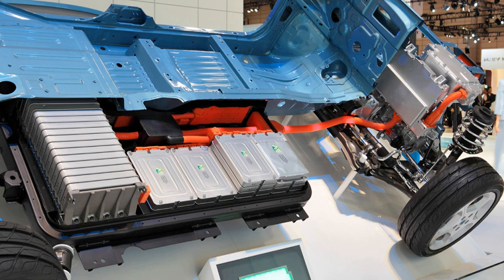Flooded lead-acid batteries are the cheapest and historically the most common traction batteries available. There are two main types: automobile engine starter batteries and deep cycle batteries. Automobile alternators are designed to provide starter batteries high charge rates for fast charges, while deep cycle batteries — used in electric vehicles like forklifts or golf carts and as auxiliary house batteries in RVs — require different multi-stage charging. No lead-acid battery should be discharged below 50% of its capacity, as it shortens the battery's life.